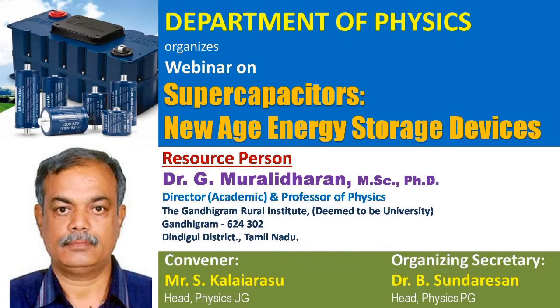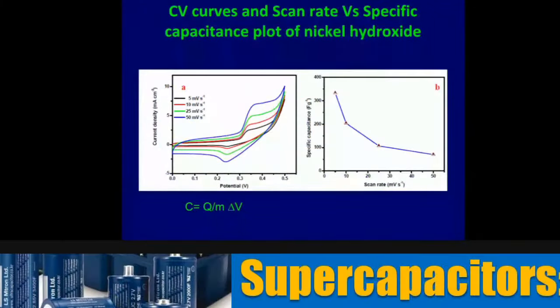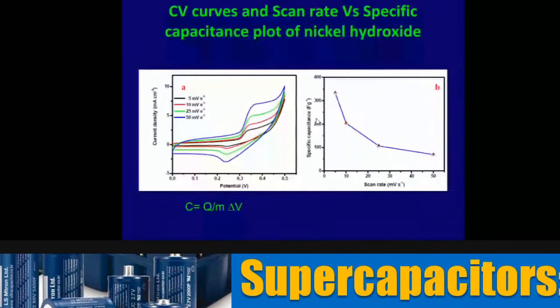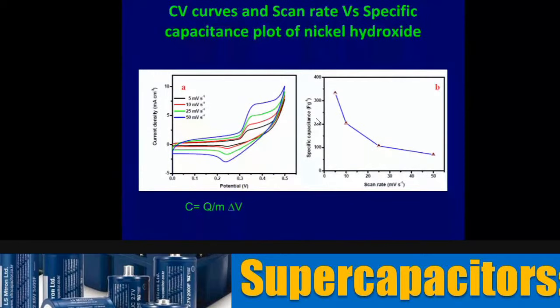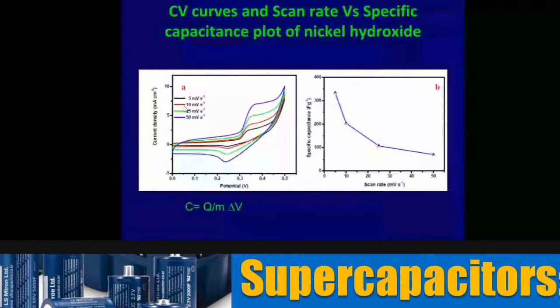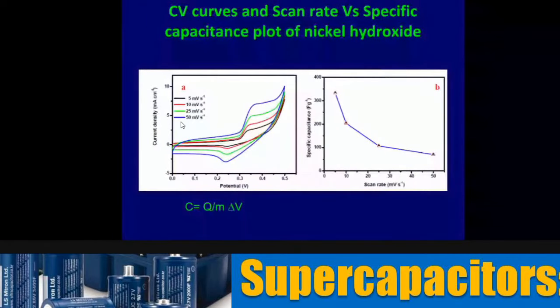This is a typical CV graph. What you see on the left side is called the cyclic voltammogram. The current is plotted against the applied potential. You can see that the lines go and you see peaks. These peaks are indicative of the reduction, and similarly when it comes back, you see that in the positive direction around 0.35 volt a peak is there, in the negative direction around 0.25 volt there is a peak. These are known as the redox peaks.